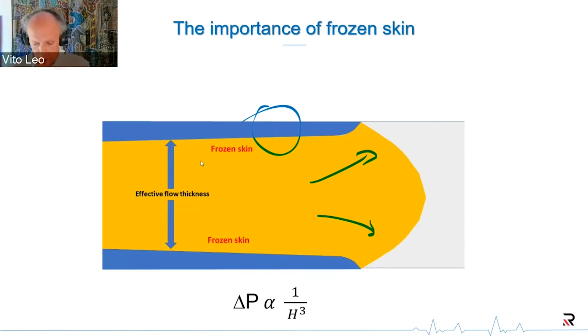So whenever you mold, conventional molding, your mold temperature would be somewhat below the glass transition if it's an amorphous material, and certainly below the melting temperature if you're molding a semi-crystalline material. In both cases, it means that the contact between the melt and the steel of the tool will rapidly form a thin frozen skin. Now, it turns out that this frozen skin has a variable thickness.